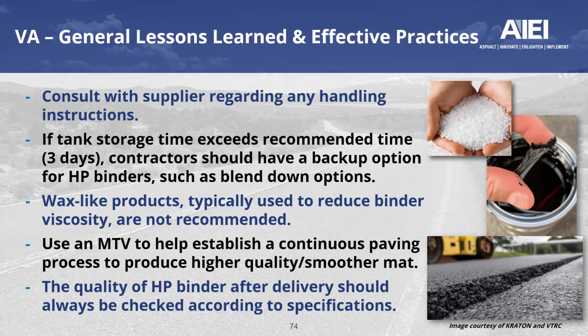Also, according to the contractors, wax-like products that are typically used to reduce binder viscosity are not recommended. They also recommended the use of a material transfer vehicle, MTV, to help establish continuous paving, and that will lead to a higher quality and smoother mat. And VDOT personnel, as well as contractors, recommended checking the quality of HP binder upon delivery and even during production, by sampling and doing extra testing at a frequency that's slightly higher than the typical frequency of testing asphalt binder for conventional jobs.